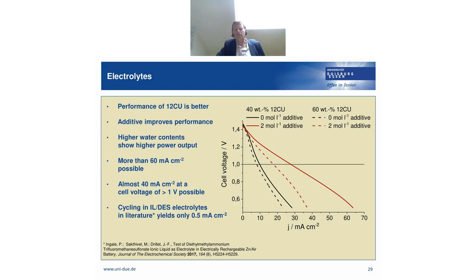We have typical current voltage curves here. We have current densities up to around 60 milliamps per square centimeter. But of course, interesting is the operation point around 1 volt. So at around 1 volt, we have a current density of 40 milliamps per square centimeter. And our project goal was to achieve around 50 milliamps per square centimeter. So we did not reach it exactly, but we're quite close to it, especially when you consider that in the literature on ionic liquids and deep eutectic solvent electrolytes, generally current densities in the range of 0.5 milliamps per square centimeter are reported.